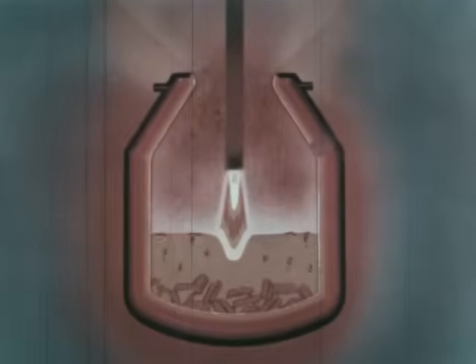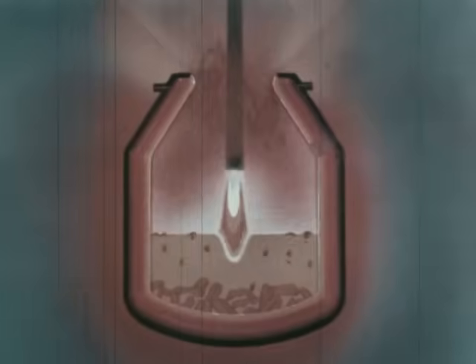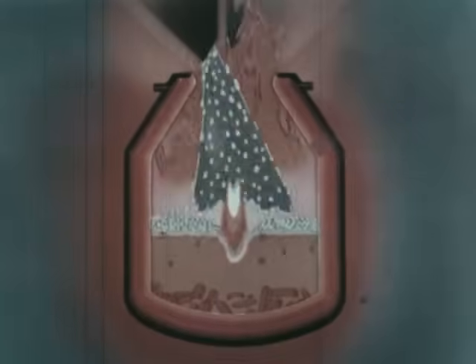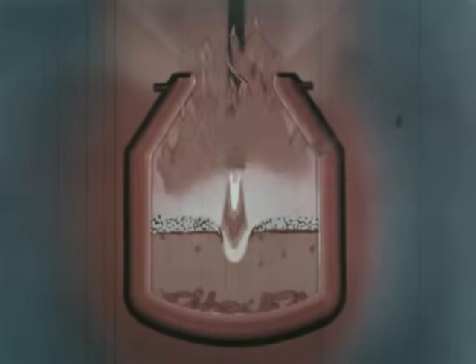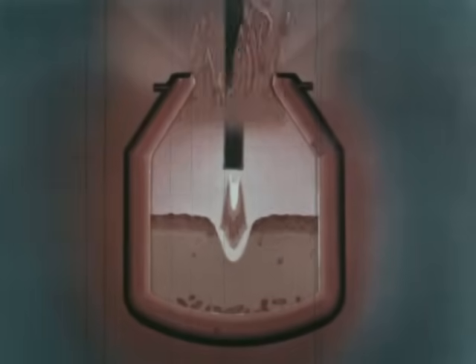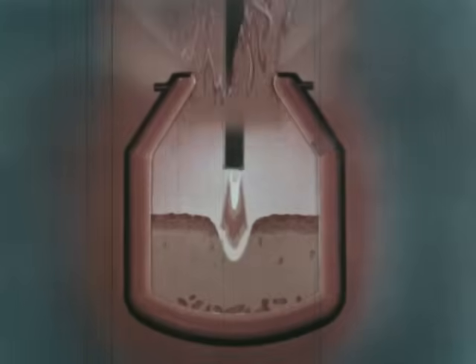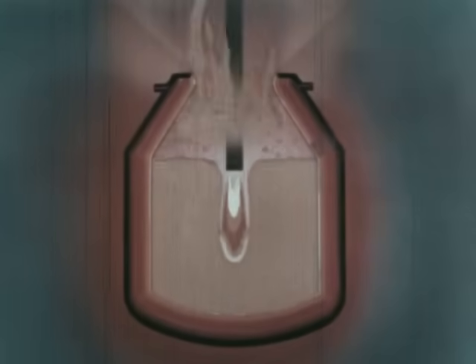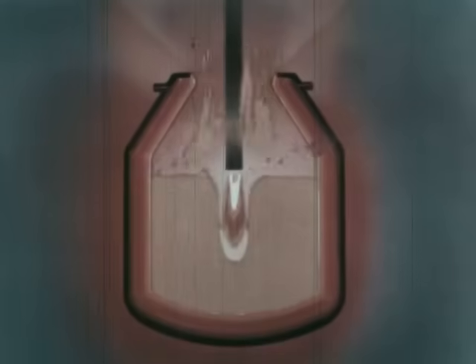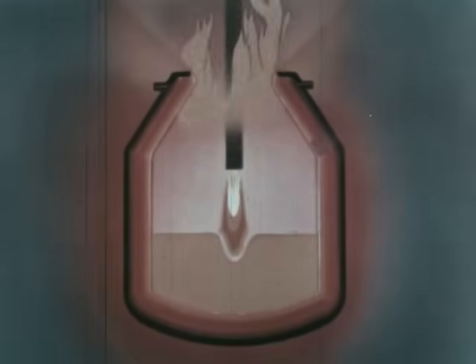As the carbon in the iron begins to react with the oxygen, carbon monoxide is generated. When it reaches the atmosphere at the mouth of the furnace, it burns to carbon dioxide, producing a brilliant orange flame. Soon after the oxygen blow begins, fluxing materials, principally burnt lime, are added. As oxidation proceeds, a liquid slag forms on the surface of the bath. Within about 15 minutes, the carbon content of the charge is down to about 2%. At 26 minutes, oxidation is complete. The carbon is down to the desired level, and the heat is ready to be tapped.